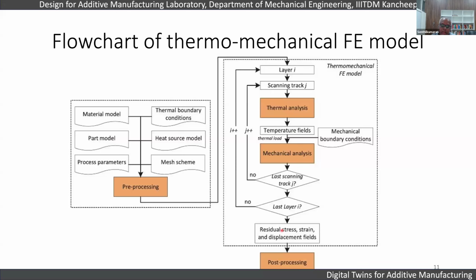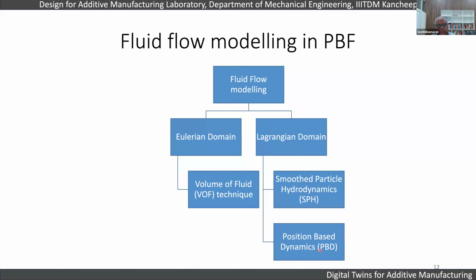Then calculate the residual stress, strains and displacement fields at the mesoscale after you have the temperature field, which you have collected over the thermal history, let's say for example T of x, y, t is the temperature that you got over time. Then you use that to calculate the residual strain and displacement field using that coupled thermomechanical analysis and do the post-processing to visualize the results.